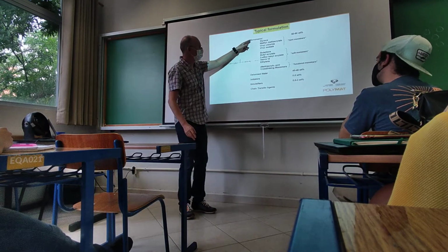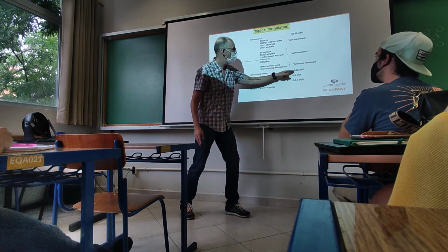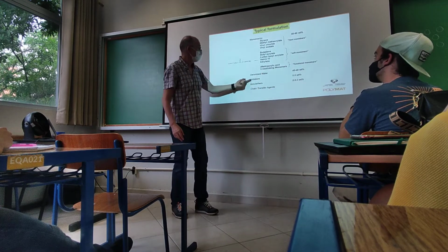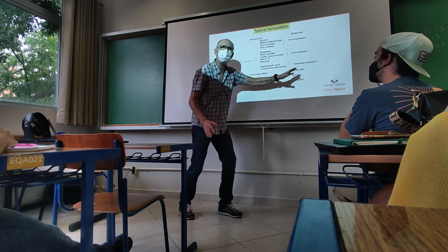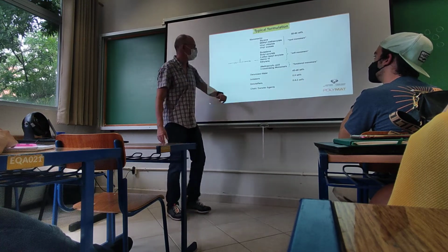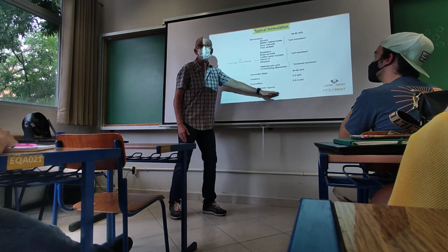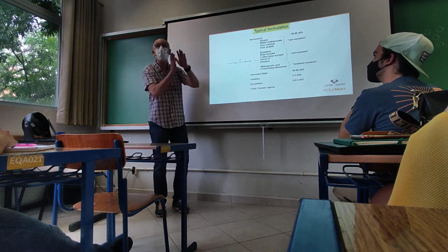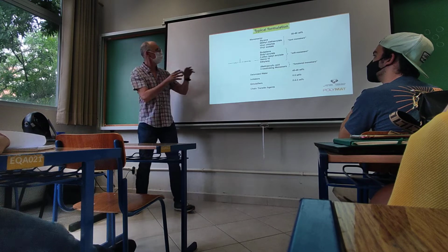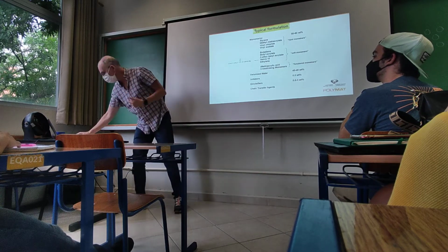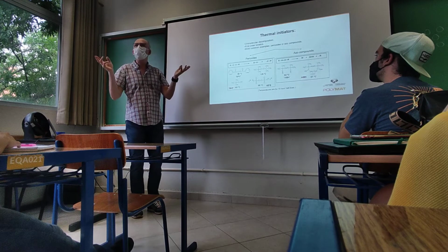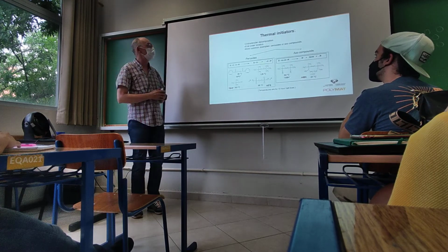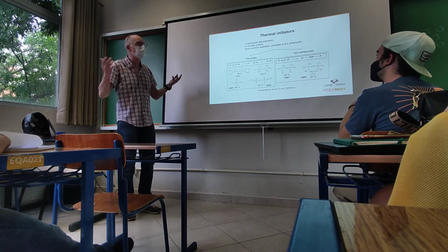Okay, so in addition to the monomer, you will have water, 40-45%, initiators, 0.5, surfactants or emulsifiers, depending, 0.5 to 3%, and we can also have chain transfer agents in the formulation to control molar masses. So this is the typical formulation. Let me go to the most important components, because the others you probably know. The chain transfer agent you know from homogeneous systems. The cross-linkers you also know.